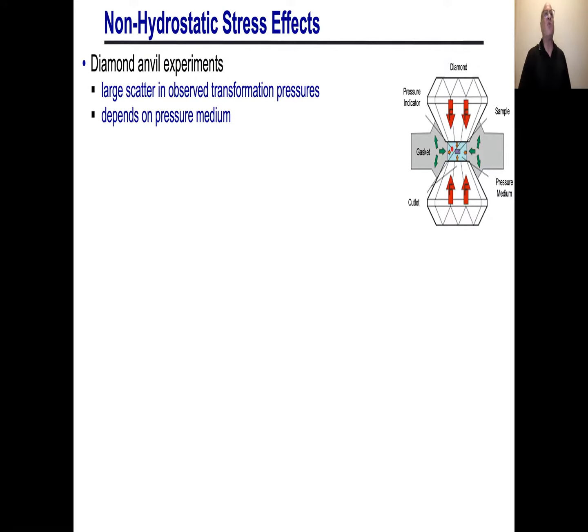Okay, so what are some of the indications that these non-hydrostatic stresses are important? Well, the first one is that if you look at the transformation pressures, typically they show a very large range of transformation pressures, even in almost very high purity materials. And as I'll show you in a little bit, it depends on the pressure medium.